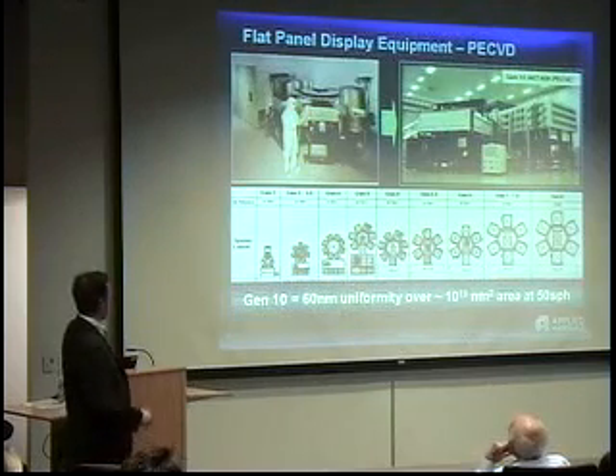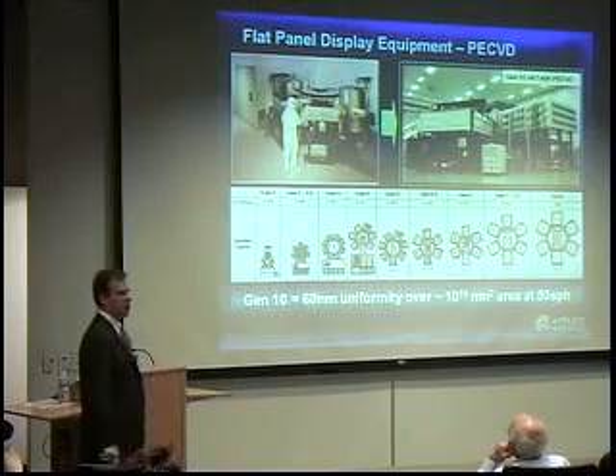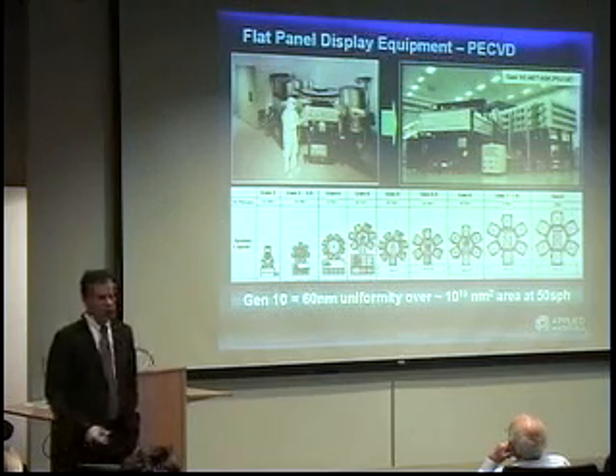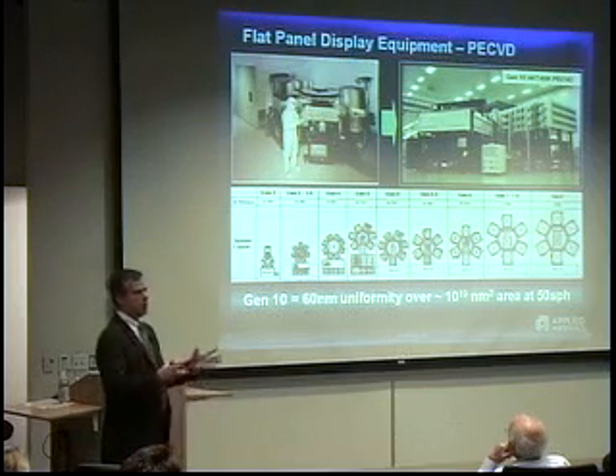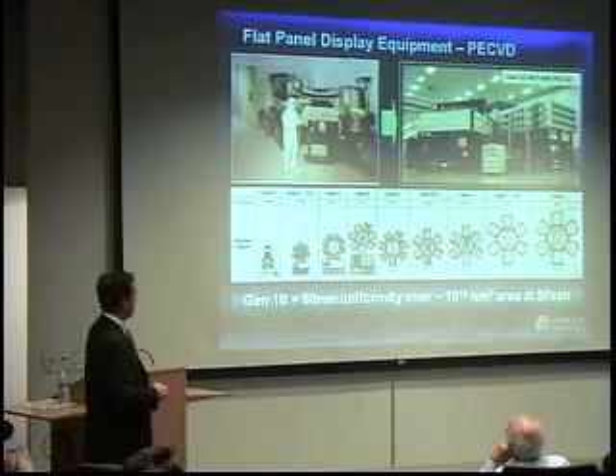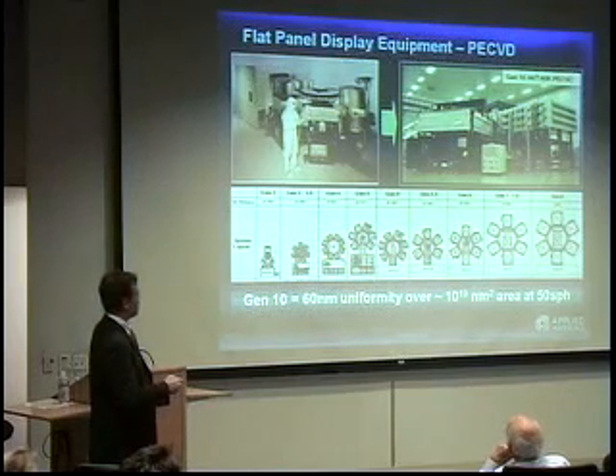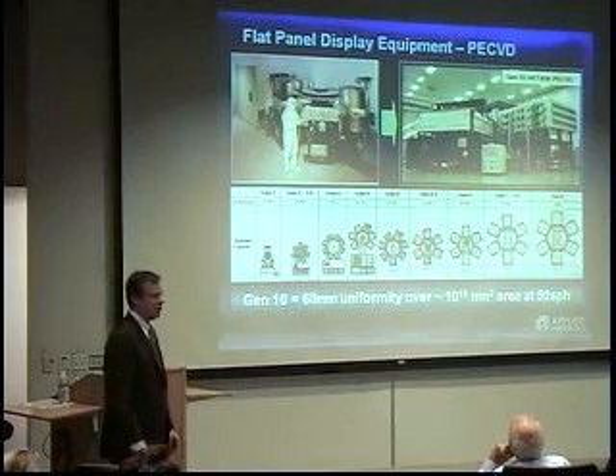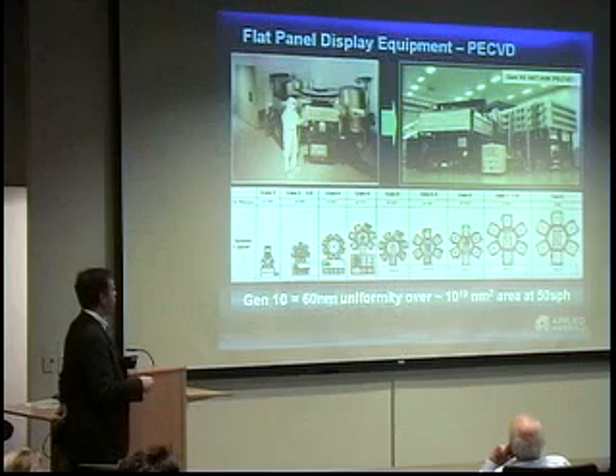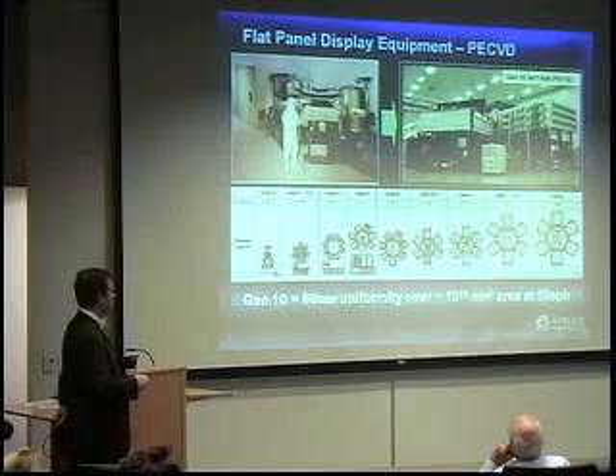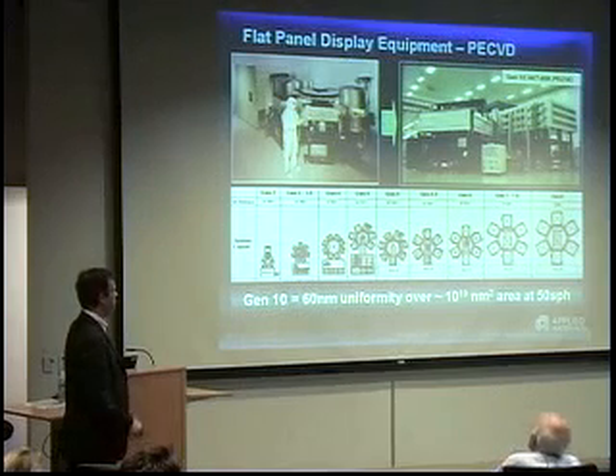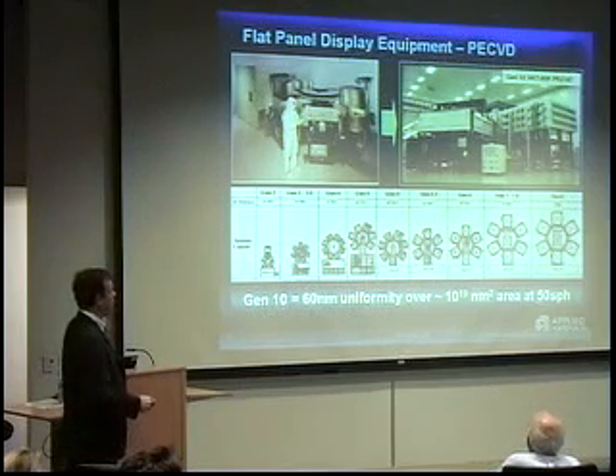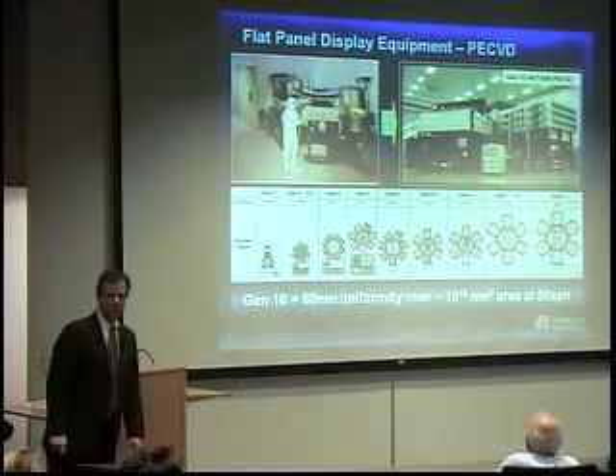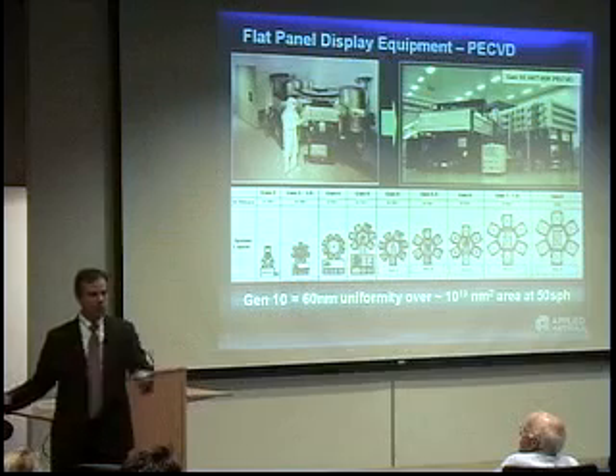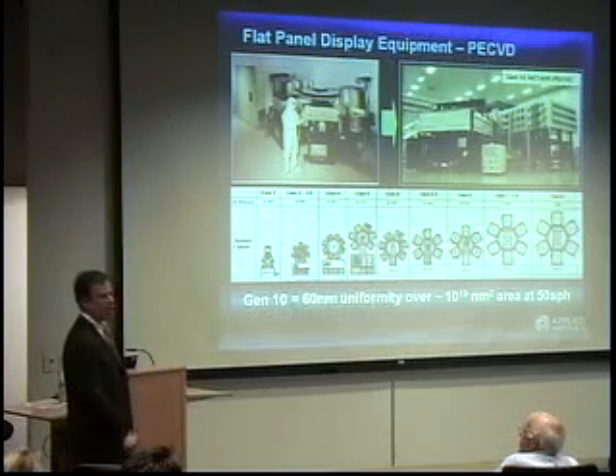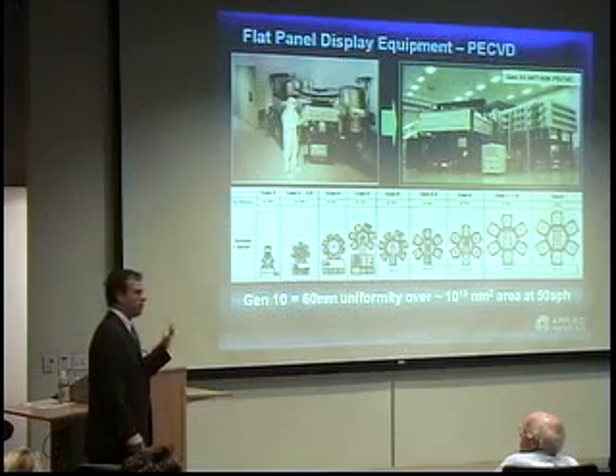So this just shows you when Applied entered the flat panel business, the tool looked like this. It wasn't much bigger than a semiconductor tool. In fact, the company thought this was a good idea to get in this market because chips were going to use the same size very shortly. But what they didn't realize was every 2 years, we started scaling up, and this is the latest tool we have now. It's 9 square meter substrates, pretty big. But it's important to realize that you're getting nanometer level uniformity, but it's over a huge, huge area. And we do over 50 of these substrates going in and out of one of these machines. So imagine 50 garage door size substrates going in and out of this machine an hour, all having to have films with this kind of uniformity. That's what this business is about.